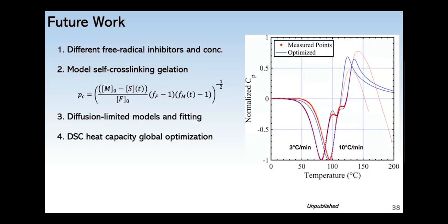And if I was to carry out my work further, I would consider trying different radical inhibitors and maybe concentrations. I would also try to model the self-cross-linking gelation at high temperature for the first few hours. I thought maybe you could do this by updating the initial maleimide concentration term and making the average functionality a function of time. That's one thought I had.